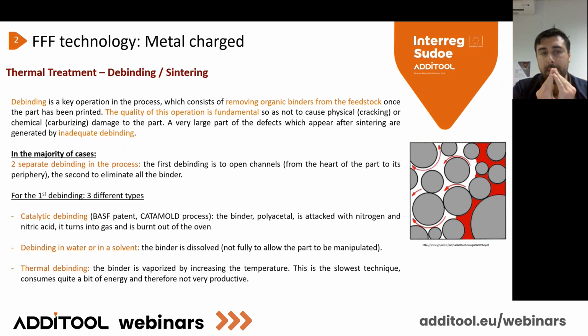The second type of debinding is the debinding in water or in a solvent. That is the technology of Markforged, for example, where the solvent is Opteon. The binder is dissolved, but not fully. In the first debinding, we don't debind the part fully, it's just to allow the part to be manipulated. Okay, so we debind a little bit, about 50%, more or less. We create channels, and so then we can have a thermal debinding after.